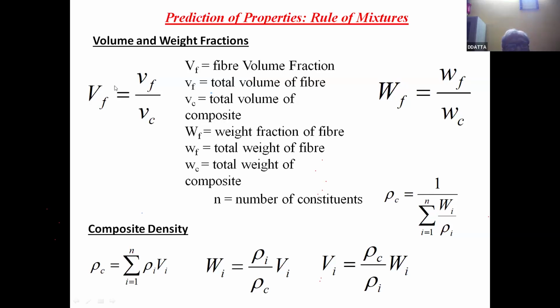And it can be shown that the sum of the volume fractions of all the constituents will make it 1. Similarly, for the weight fractions also, the sum of their individual constituents will make it 1. We can also find the density of the composite by this simple rule, rho = sigma rho_i V_i, where i is the ith constituent, rho_i is the density of the ith constituent, and V_i is the volume fraction of the corresponding ith constituent. So it can also be expressed as this. This is a relationship between weight fraction and volume fraction. And this.